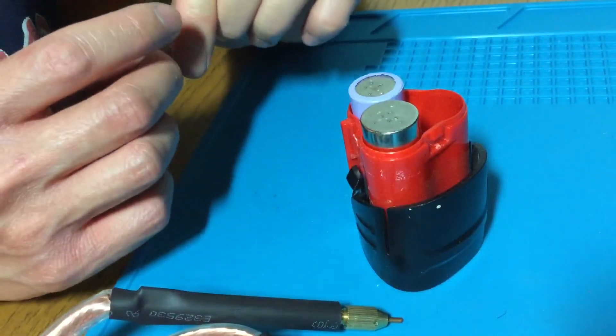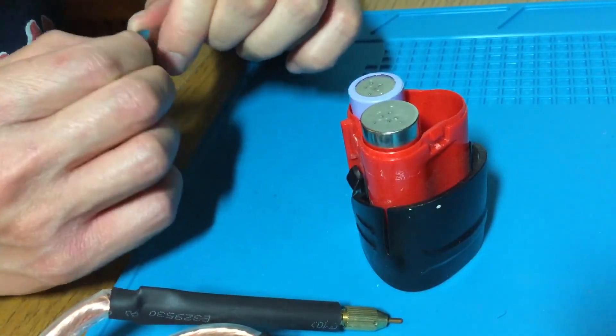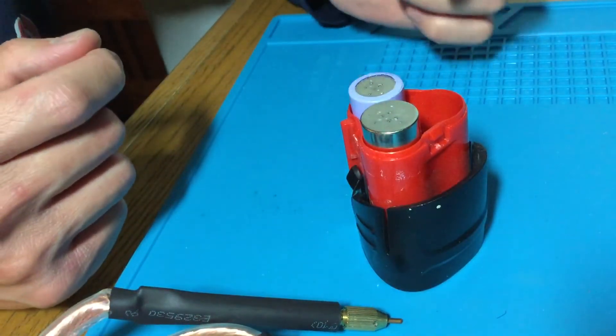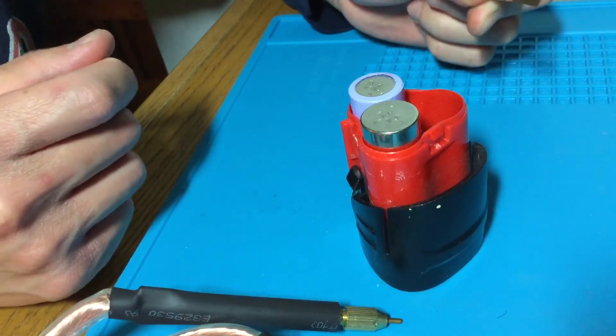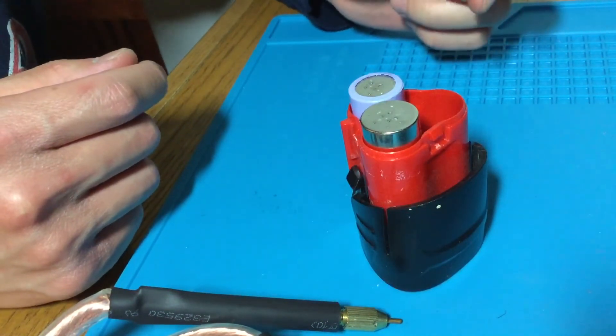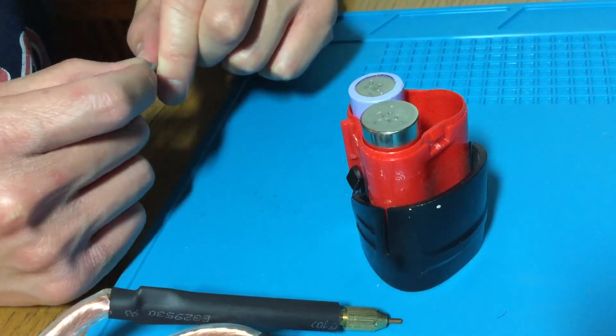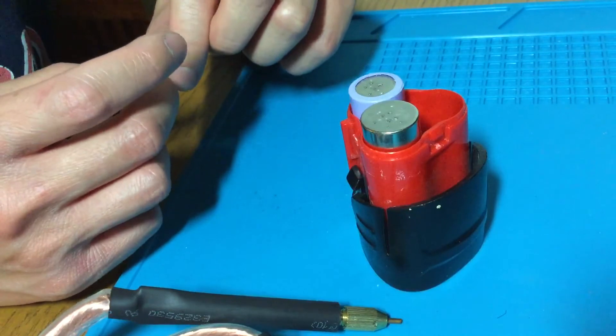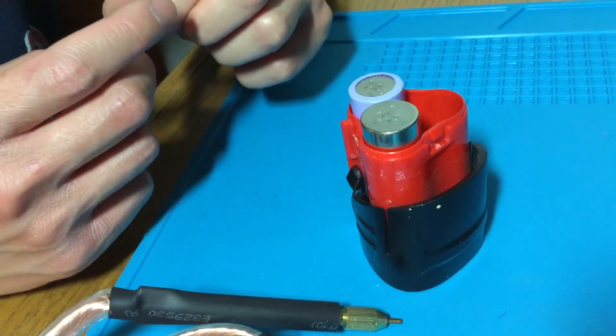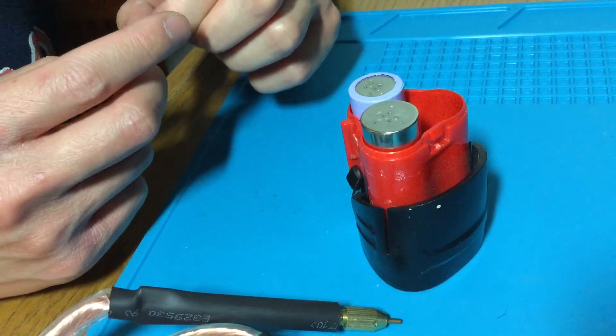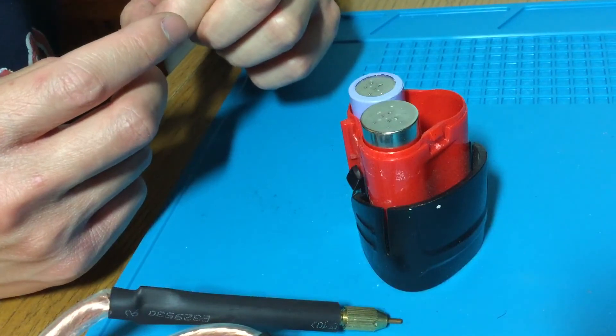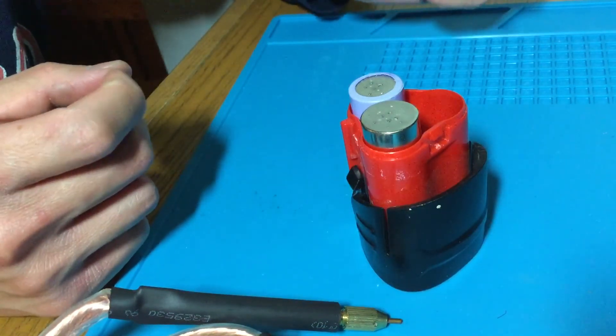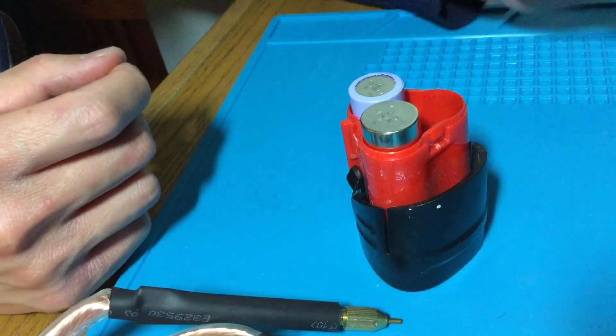So, I'm guessing that's your conclusion. If you want to do 0.2 pure nickel with this 5,000 watt spot welder, it's not going to happen. So, kind of limited to 0.15. And based on the other video that you watched, it was not pure nickel strip because it sparked a lot. These things didn't spark, so at least this is pure nickel strip.